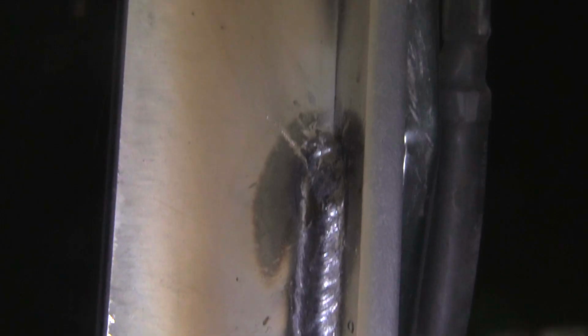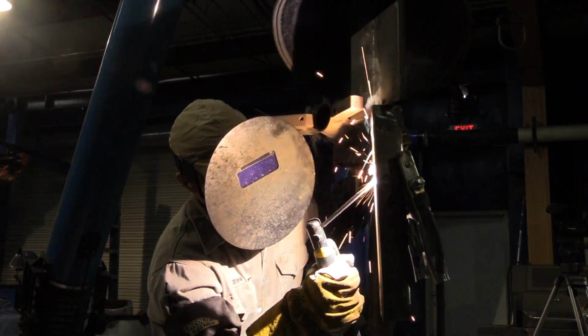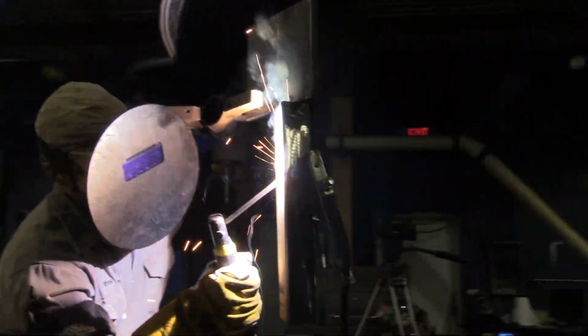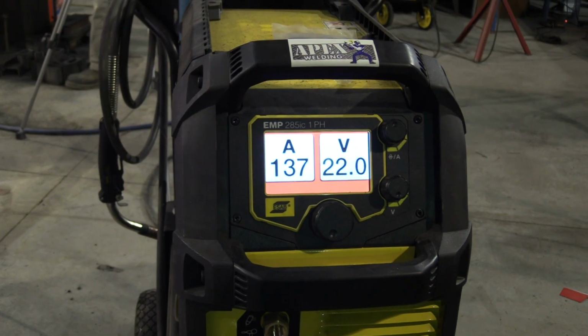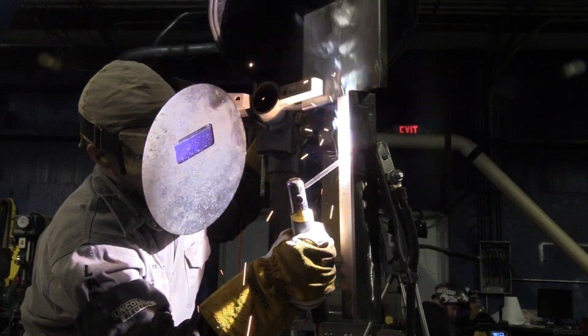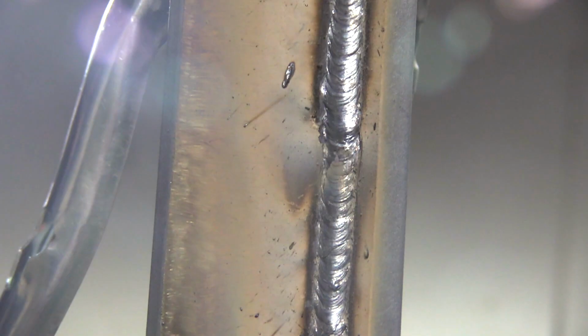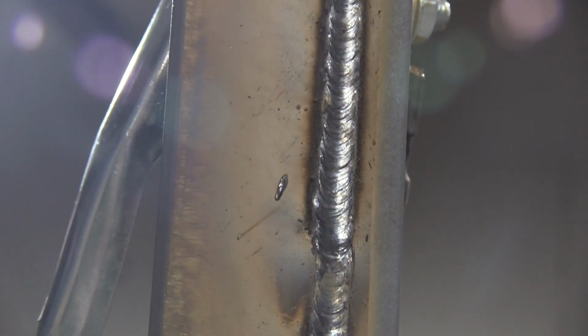Looking good. All right, our restart technique is to avoid any arc strikes. So Andrew's going to strike up ahead of the crater by about an inch. And you see it deposited some spatter and some stuff there. And he's just going to weld right back over it. That's the technique to avoid arc strikes. Make sure to weld back over any arc strikes that you do happen to have. It also lets the 7018 heat up just a little bit and prevents porosity there on the tie-in. And you see that's the restart, the tie-in right in the middle there.